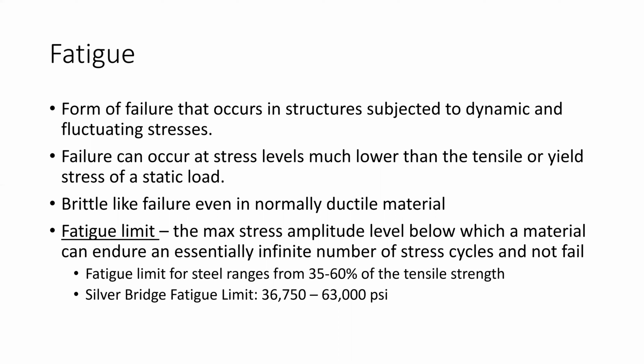Fatigue causes failure to occur at stress levels much lower than the designated yield or tensile stress of a static load. The stress level just before reaching this failure point is called the fatigue limit. A fatigue limit for bridge materials, often steel, ranges from 35 to 60% of the tensile strength. In the case of the Silver Bridge, it was made of a newly invented, high-strength, heat-treated medium carbon steel that had an ultimate tensile strength of 105,000 psi. This puts its fatigue limit between 36,750 psi and 63,000 psi.